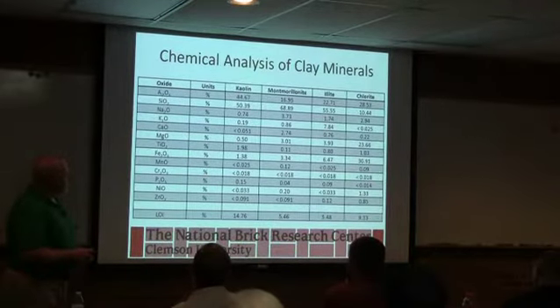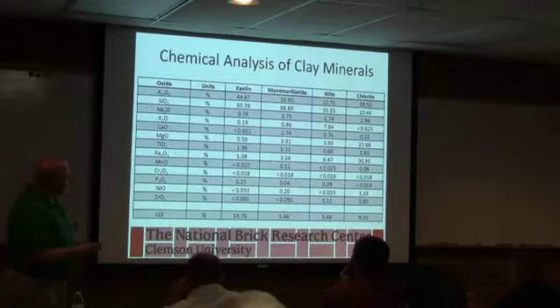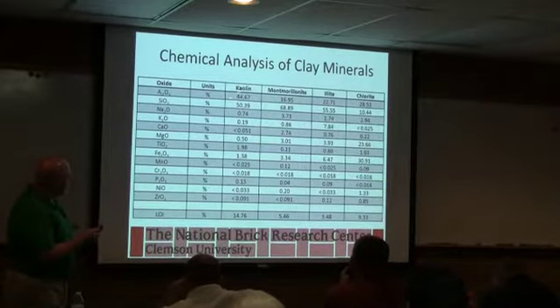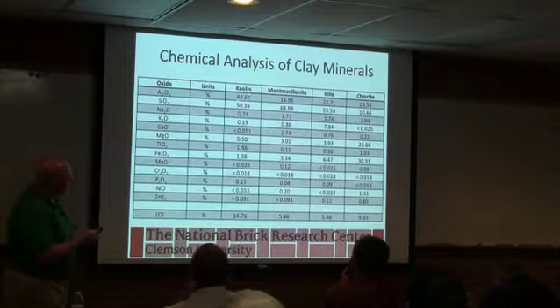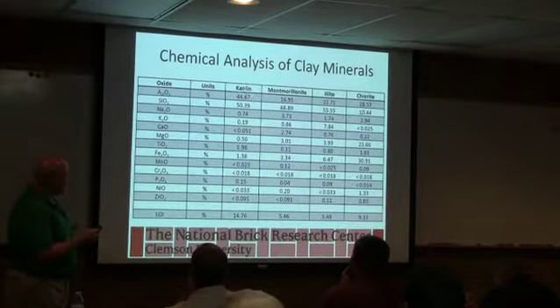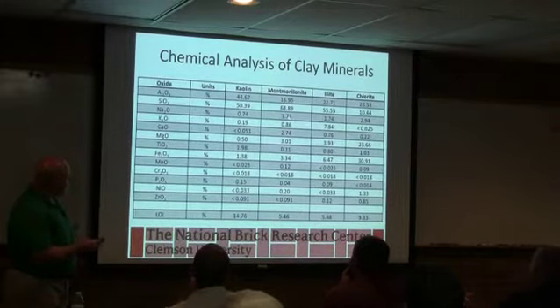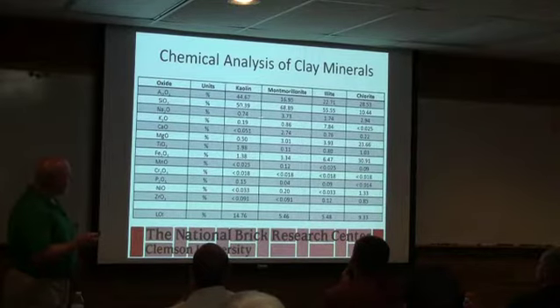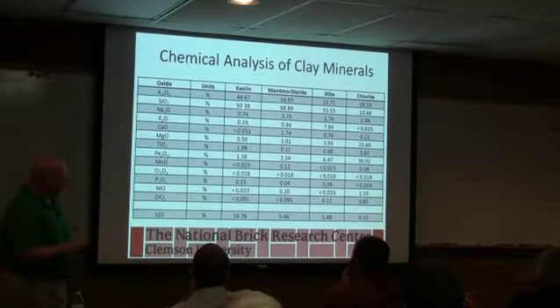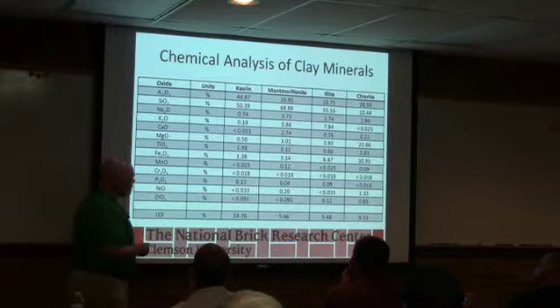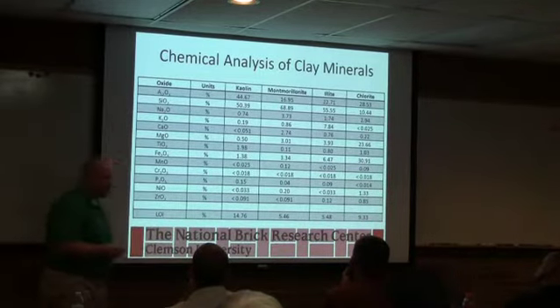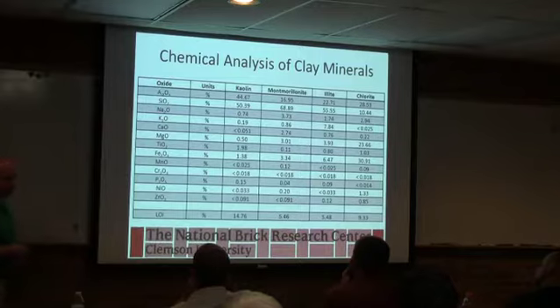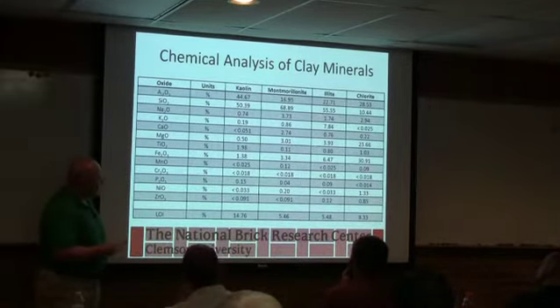We'll talk about that. So these are chemistries of the different clay minerals, and remember I said alumina is usually a good indication, especially if we're talking about kaolin. So you can see a pure kaolin's got a high alumina content. Typically, with the exception of the montmorillonite and the illite, they don't have a lot of fluxes. This is a pure kaolin. I've got to get it up probably 2500 F to get any meaningful vitrification taking place.